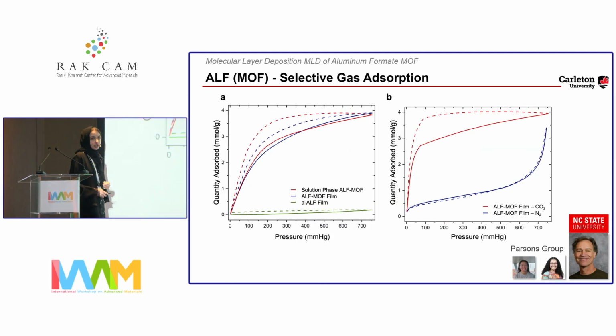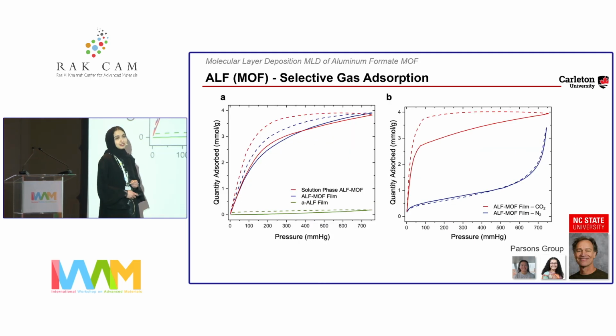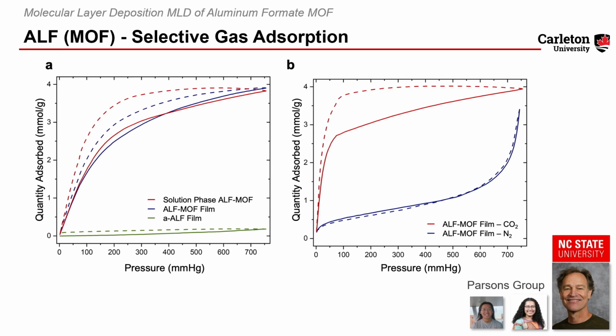Now, the cherry on top is whether it can absorb carbon dioxide selectively. So this graph over here compares the as-deposited MOF. You can see this is carbon dioxide adsorption, no adsorption whatsoever. And then if you compare it to the bulk right there, you can see it's a very comparable trace. And the second you start introducing carbon dioxide, you see uptake. And then we try to take it away. It doesn't want to give it back.